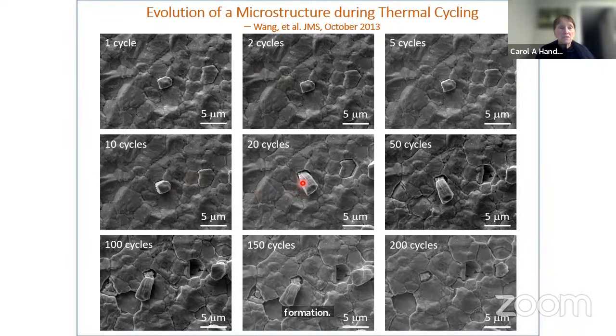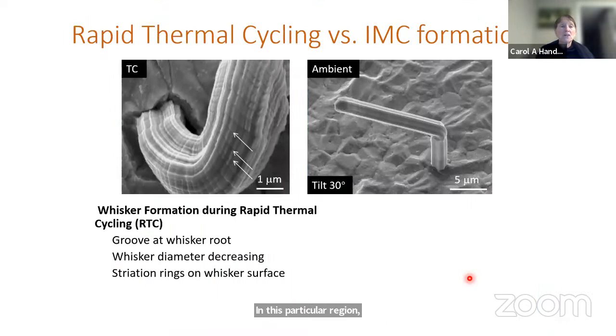There's more whisker formation with 20 cycles, but what we're seeing is actually there's a decrease in diameter as the whisker grows. We see twinning, we see new whiskers growing, and we also see a phenomena where the whiskers actually pinch off. In this particular region, these grains actually sank. So in the whisker formation during rapid thermal cycling, what we see is that if we're thermally cycling it, we go to high temperatures, so the film's under compressive stress, low temperatures, it's under tensile stress because it's relaxed in between. So we see this grooving at the whisker root.